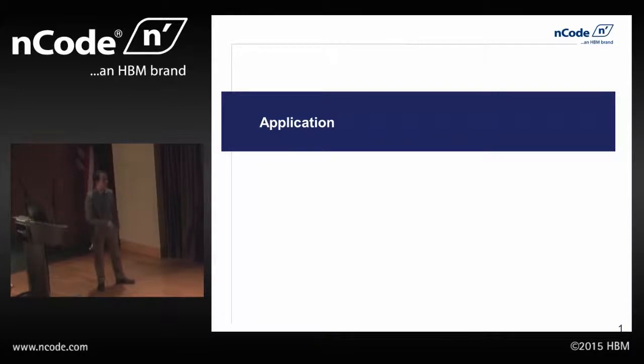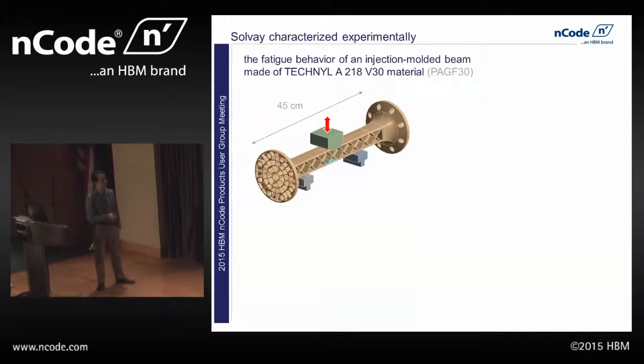So we can look at how that might be applied. In this case, the application we're talking about is a relatively simple application. It's a great application, though, I think, for demonstrating this technology because it's not so complex that it's difficult to understand, but you can see it's got these varying rib features that are happening through here, and so that gives us some really interesting things where the fibers tend to align down the direction of those ribs, and then at these joints right here where you have basically two flow paths coming together, you get these little balls of randomly aligned fibers. So it's a relatively simple geometry, but we get some really interesting microscopic effects happening.